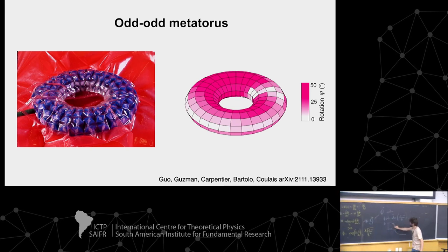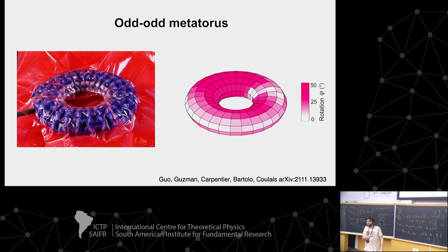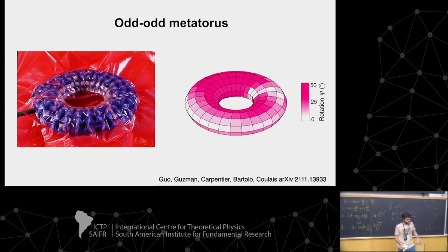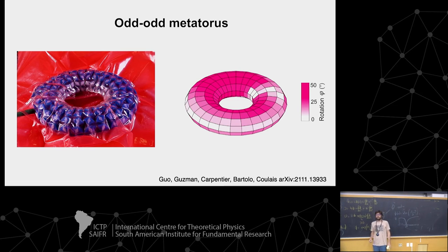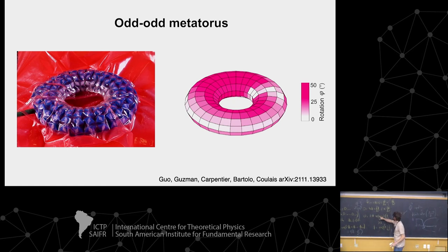So instead of having a full soliton, what you end up with is two half kinks that have to vanish at a point S star. That's just because of the topological constraints that come from this non-orientability. Otherwise, the width of this kink is given by the same characteristic length scale as previously. You cannot counter-rotate everywhere, so you have to accommodate some gradients by virtue of the topology, and the characteristic size over which you do that is given by alpha, but also a bit of the p, because you see that here the p also comes in at the linear level.